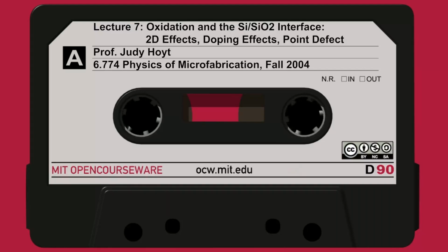Let me just show slide 35, to compare boron and phosphorus. We know from our calculations, just because of the point defect statistics, that N-type regions tend to have higher charged vacancy concentrations at a given dopant level than P-type, than boron. And in fact, what we see is that the B/A parameter is more impacted in very heavily doped N-type silicon than it is in P-type. That's the difference between the right and the left-hand side on page 35.